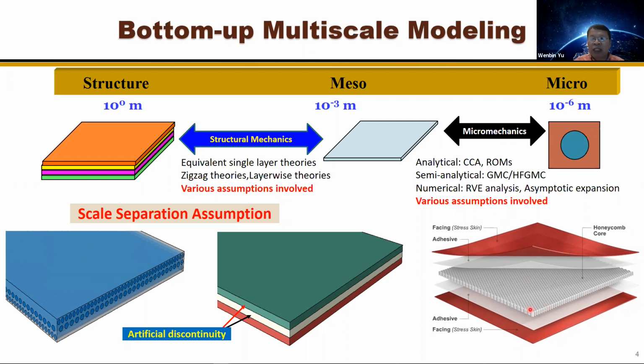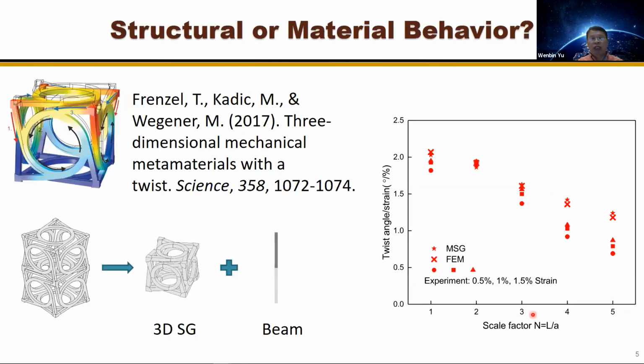The reason being that the size of the honeycomb is similar to the thickness of the panel. So when the scale separation is not clear, it's not at that 3-dimensional material level, but at the panel level, which means the thickness and the size of the microstructure should be considered together to do the homogenization. And this kind of bottom-up thinking sometimes also confuses structure behavior and material behavior.